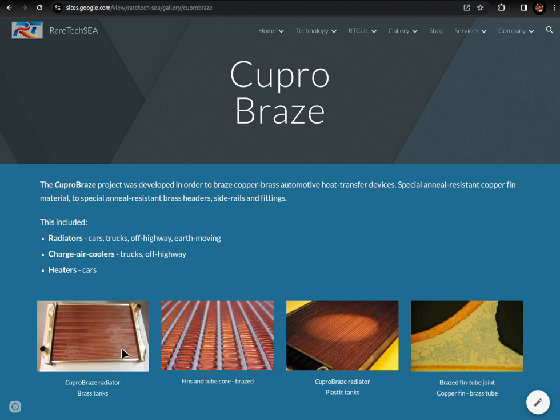So this is what was coming out of the brazing furnace. And this is an example of a brazed core. What you have here is the anneal-resistant copper fin, and you have the brass tube. The brass tube originally starts off as a yellowy color like you'd see here or here. But what happens is the braze alloy actually wraps all the way around the tube. And eventually, this is the color of the final braze alloy.